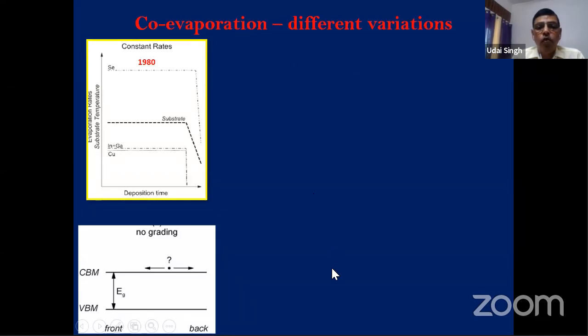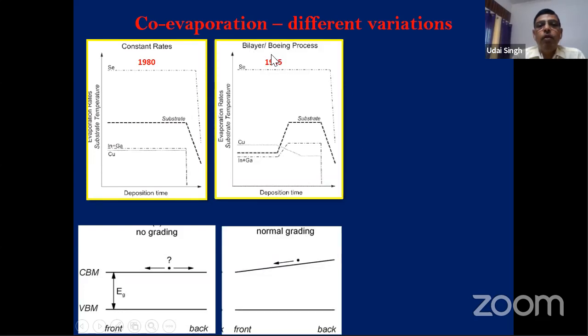So in co-evaporation, there are different variations one can have. Initially, you keep the substrate temperature constant, the selenium flow constant, and deposit copper, indium, gallium at constant rates. So you get a band gap with no grading. After that came the bilayer or Boeing process, because the Boeing company developed this process. Here you have constant selenium flow, but initially the substrate temperature is lower, with more copper and less indium gallium. After that, you raise the substrate temperature to 550, reduce the copper, increase the indium gallium, and finally reduce it. So you get a normal grading structure, which was the Boeing process.